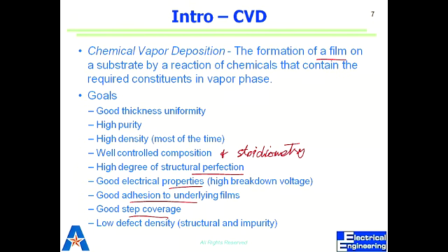And many times you want it to be highly dense, right? Maybe it's not the case, because sometimes we just need to put a sacrificial layer which we will have to etch later on, so we don't care if it's highly dense or not. All we need is to cover it completely. Composition doesn't change across the wafer. We know stoichiometry, what is the number of molecules, atoms that come together to form some network. Perfection, structural perfection, good electrical properties. Maybe we want it to be insulated, maybe we want it to be electrically highly conductive, which is the case in polycrystalline polysilicon, right? Heavily doped polysilicon.